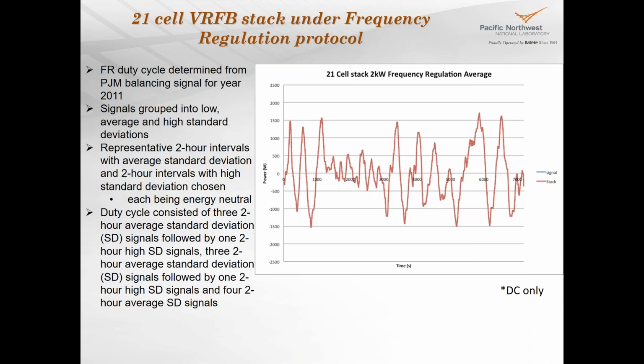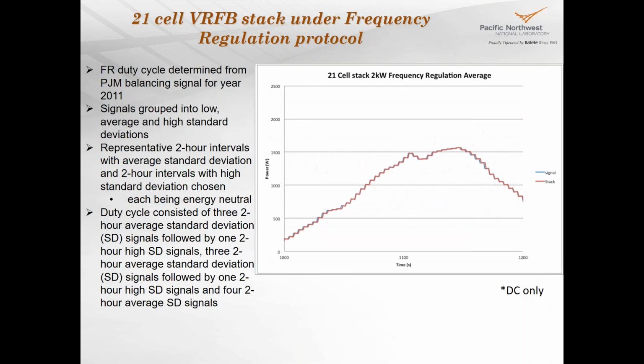The blue line is the signal, and the red line is the response from our vanadium redox flow battery stack that I just talked about. You can't see the difference at this time scale. They basically overlap with each other. And on a shorter, little over 3 minute level, you can see the red line and the blue line actually closely follow each other.